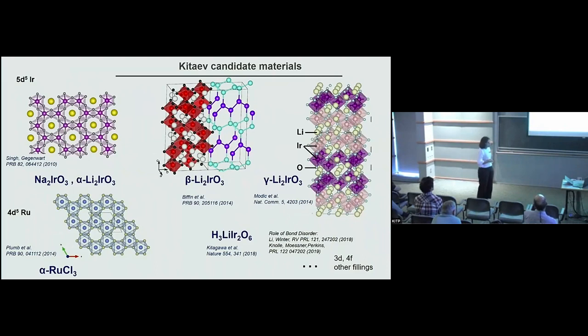However, most of these materials, maybe except for those synthesized in the group of Hide Takagi, show a ground state with long-range magnetic order. So they are not genuine quantum spin liquids. And in this case, what has been pointed out, Natalia worked a lot on that, and we also worked on that, is the role of bond disorder to explain the fact that the system doesn't order at low temperatures. So why are all these systems ordering? Why do most of these candidates show a long-range magnetic order?